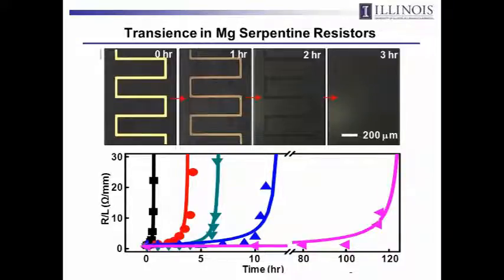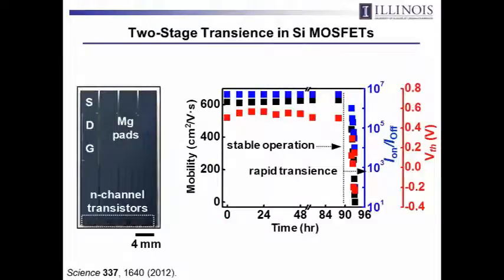You add a layer of silk. This is magnesium oxide plus silk, and you can get it into the range of a few hundred hours without too much trouble. So the point is you have a period of stable operation followed by a relatively quick period of dissolution. And you can see that even more explicitly in this transistor array.